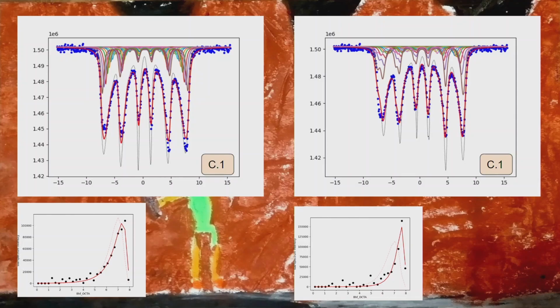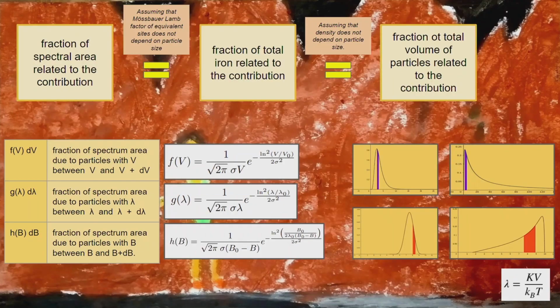We have a log normal lambda distribution that is translated to the hyperfine field in some shape. Here we have how we transform a log normal volume into a log normal lambda. It is the same, but in the hyperfine field it takes another expression. This log normal is related with this distribution, and here small particles are related with this. Higher particles are related with these other particles.